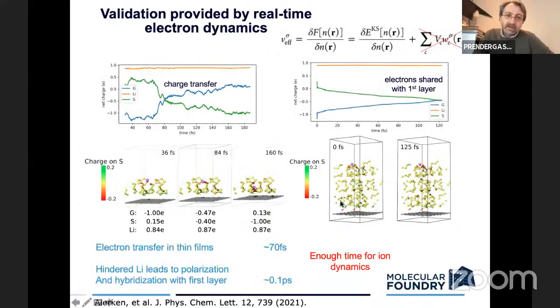Okay. All right, so in principle, that should work. That should prevent this instantaneous charge jumping out to the edge of our dielectric. And we've tested this to see, what is it relevant for? One way to do that is to start the system constrained, almost like a race where you have horses kept behind a certain line, and then release them, but to do electron dynamics. So in that case, we do real-time TDDFT, time-dependent density functional theory. And this is the evolution of the charge in the graphene. The lithium stays +1 all the time, and the sulfur.